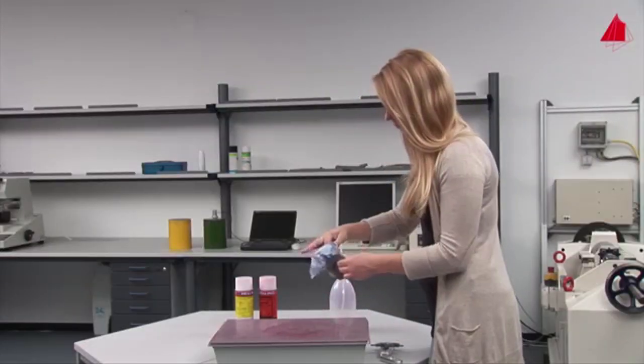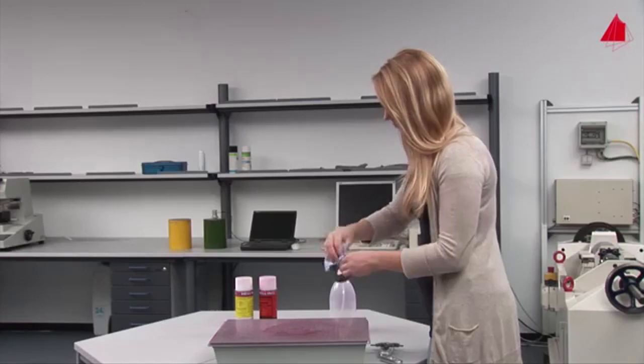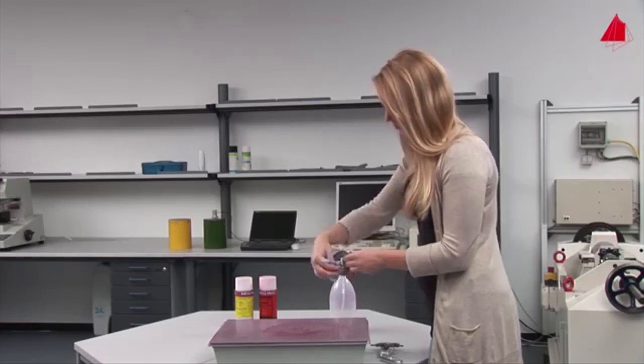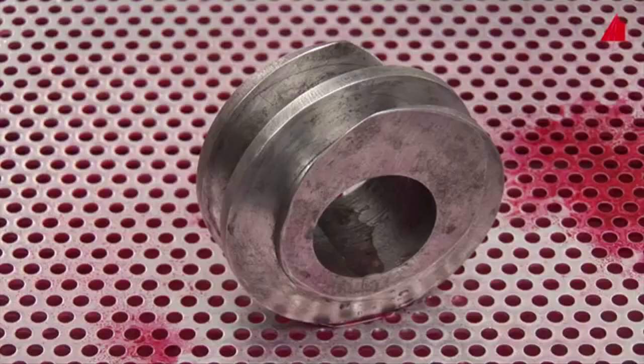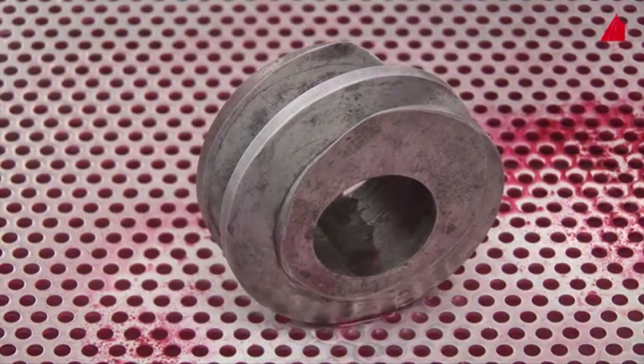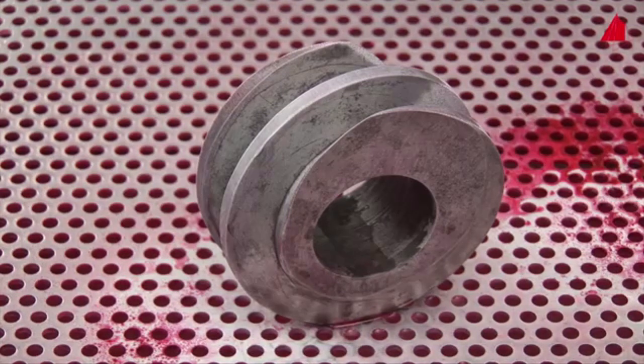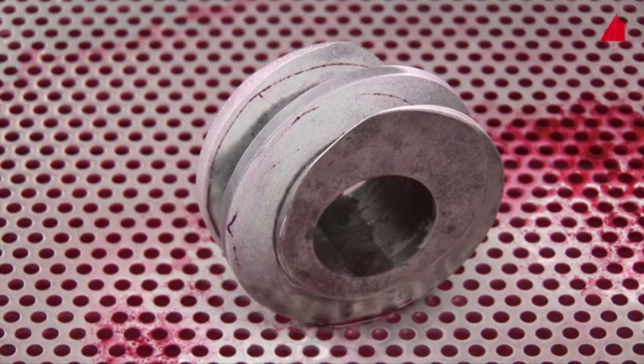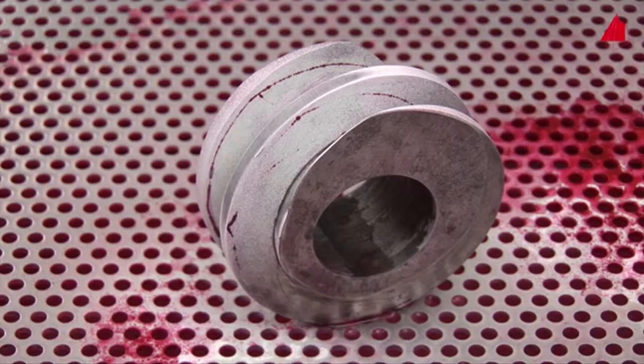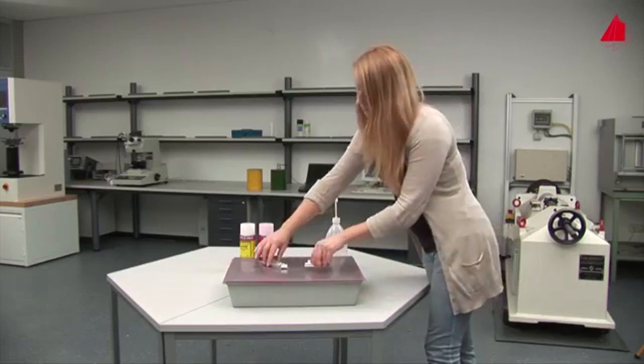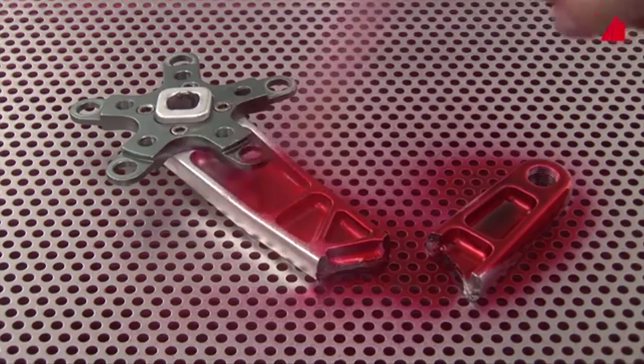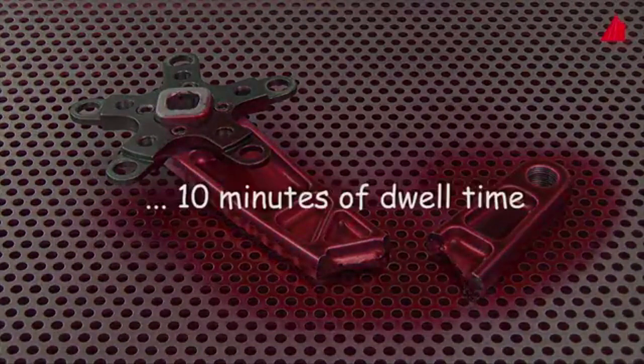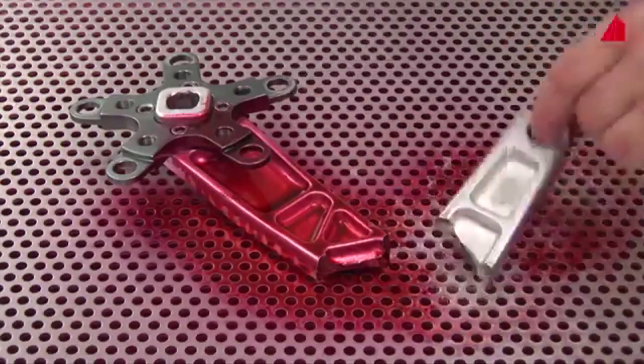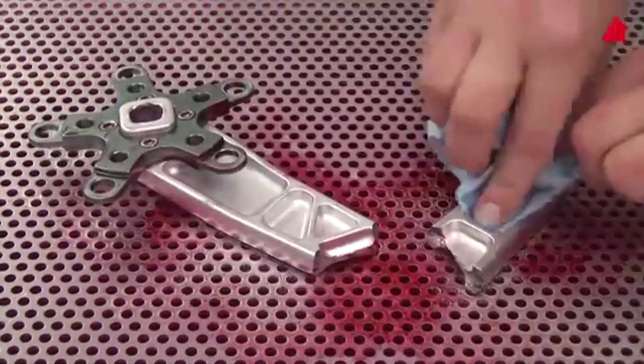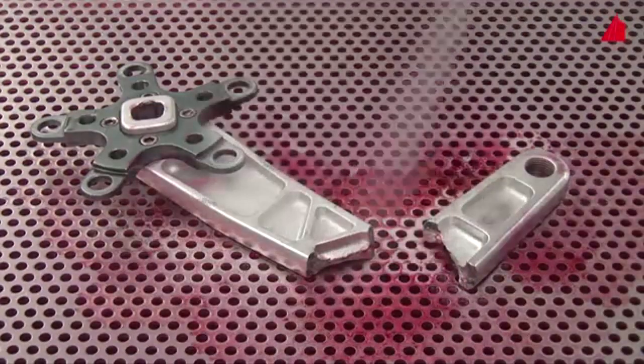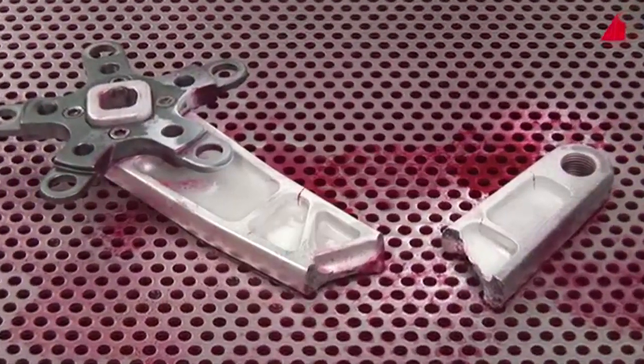Now she dries the surface of the sample with a cloth to absorb the excess water. As the final step, she applies the developer and lets it dry. That's it. Several cracks are indicated on the surface in deep red color. Next, the broken bicycle crank arm has to undergo the dye penetration test. Spraying with penetrant, allowing to soak, rinsing, drying, and applying developer. Clearly, additional cracks are indicated on the fragments.